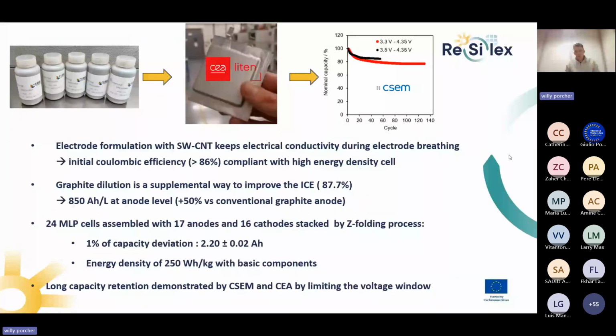So in conclusion, in Resilex regarding the activity at electrode and cell levels, we demonstrate that electrode formulation with single wall carbon nanotubes keeps electrical conductivity during electrode breathing. We achieve initial Coulombic efficiency of more than 86%, compliant with high energy density cells. Thanks to graphite dilution, we improve again the initial Coulombic efficiency to something close to 88%. And so we achieve an electrode with 850 ampere hours per liter at anode level, which is 50% more than conventional graphite anodes.